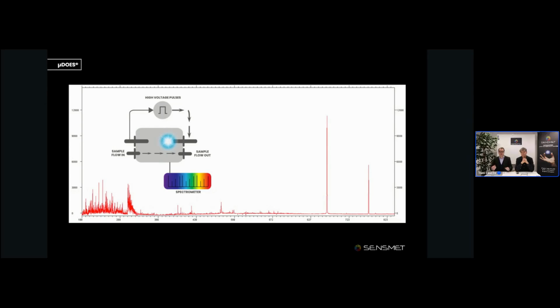Our process starts by generating an electrical discharge directly within the liquid sample at the tip of one electrode using high voltage pulses, so electricity. The controlled high voltage pulses create micro-sized plasmas within the liquid, reaching momentarily temperatures up to 10,000 degrees. The plasma excites metal atoms and ions in the sample, and as they return to their ground state, they emit light that contains the spectral signatures of the metals present in the liquid sample.